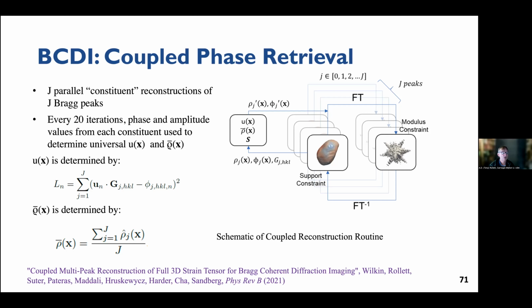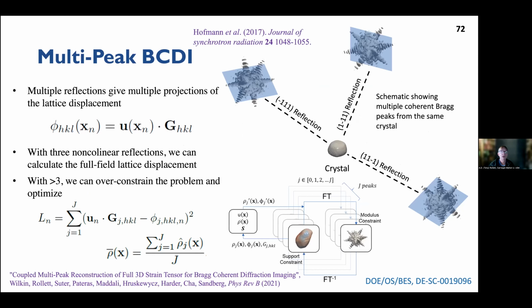And so we've been learning how to do coupled phase retrieval, where we're doing this on multiple peaks from a given grain. That was the main contribution of Matt Wilkin in my group for his thesis. There's more than one error measure. A crucial piece of this is the so-called support constraint or support function. In other words, you have to make decisions about what is the shape of the grain, but that's something you have to iterate on if you don't have independent information, but you can make it work. And so we have succeeded in doing this multi-peak Bragg coherent diffraction imaging reconstruction process.